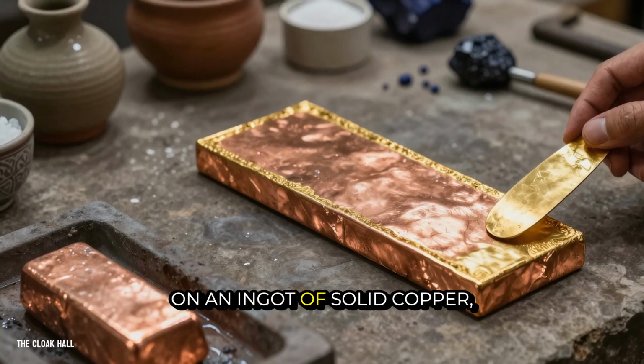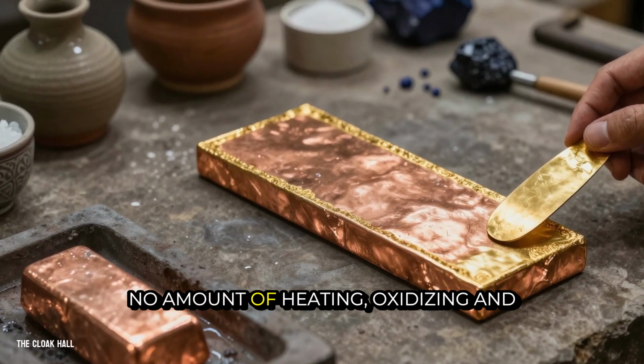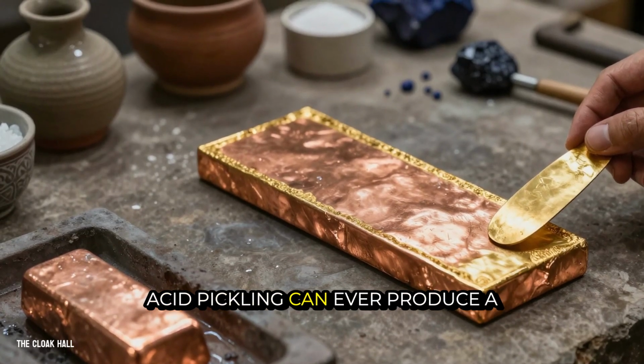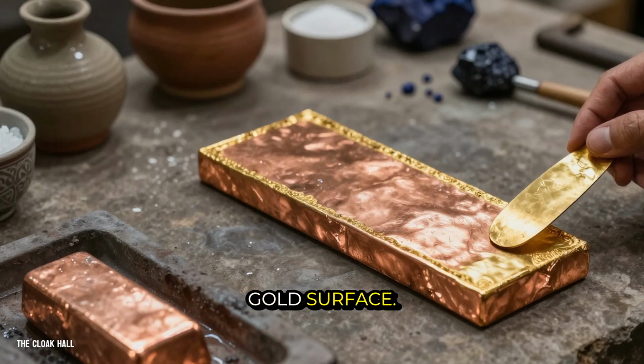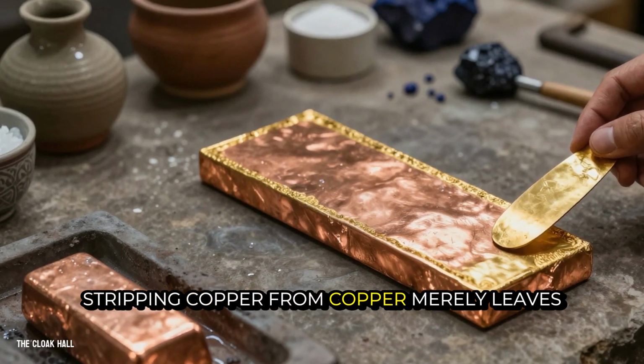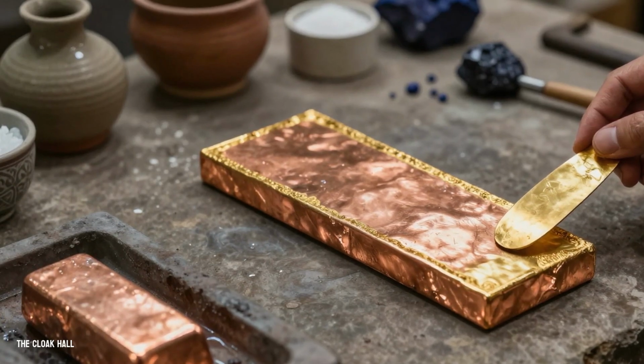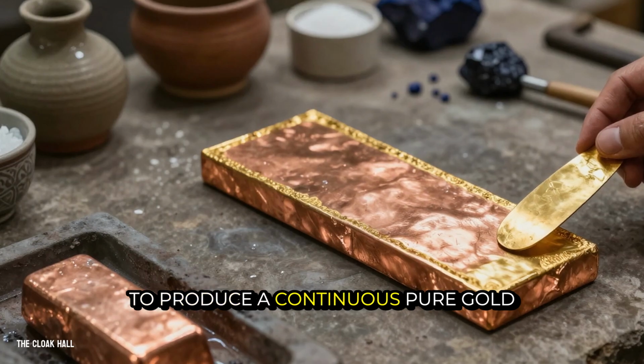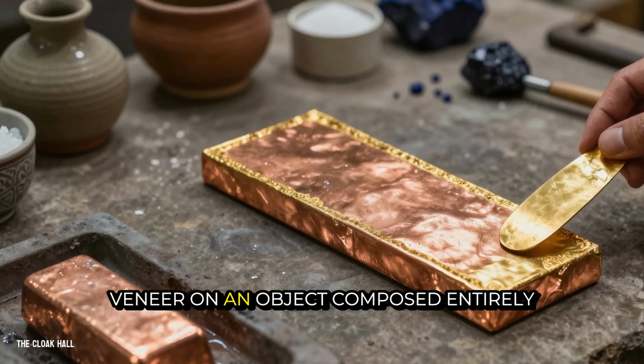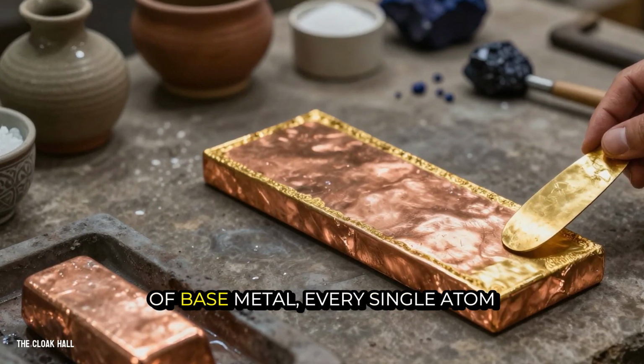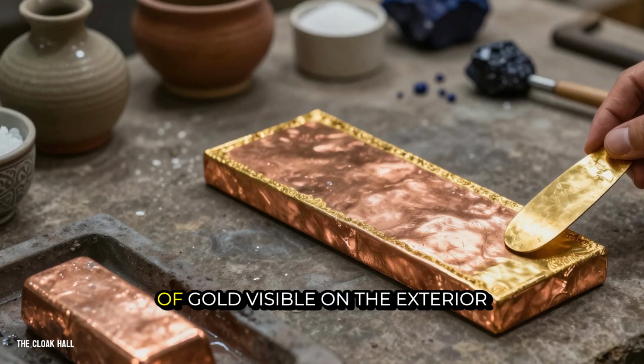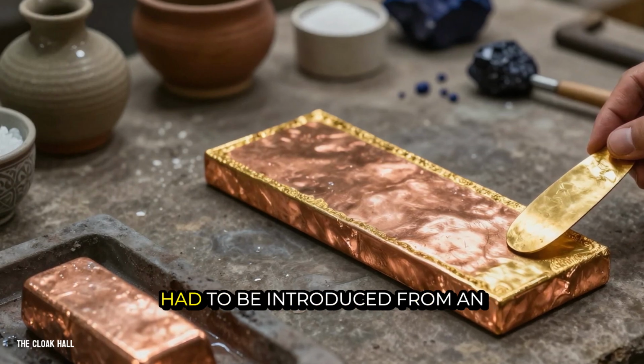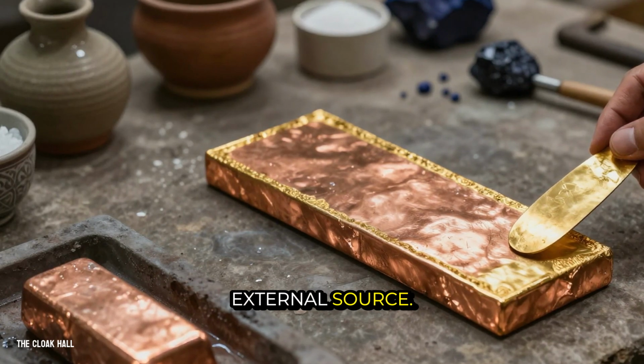On an ingot of solid copper, no amount of heating, oxidizing, and acid pickling can ever produce a gold surface. Stripping copper from copper merely leaves less copper. To produce a continuous, pure gold veneer on an object composed entirely of base metal, every single atom of gold visible on the exterior had to be introduced from an external source.